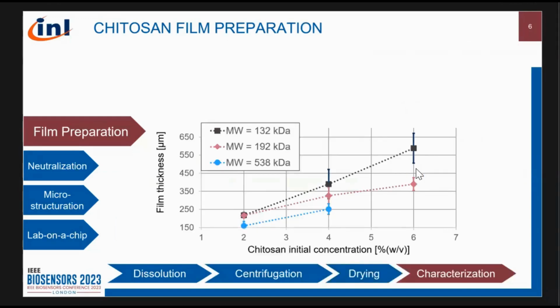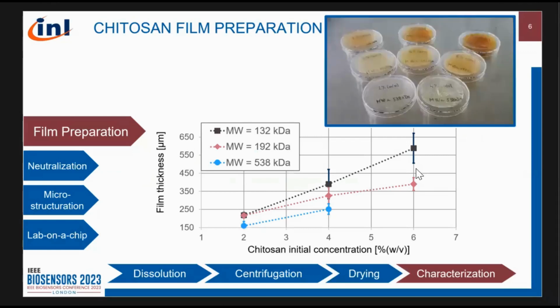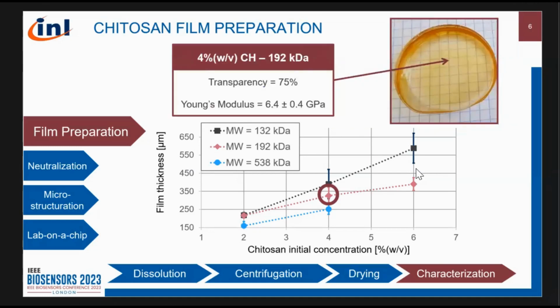After this, I characterize my films. So you can see that the thickness of the film would depend on the initial Chitosan concentration, as well as the Chitosan that I use. Depending on the molecular weight, I will obtain different films. You can see here a picture of these different films. And by compromising the properties, so the thickness and the transparency of the film, we conclude that it was better to use a medium molecular weight due to the color of the film and the thickness that we obtained. And this was the film that we studied after. We have an average transparency on the visible range of 75% and a Young modulus of 6.4 gigapascal.